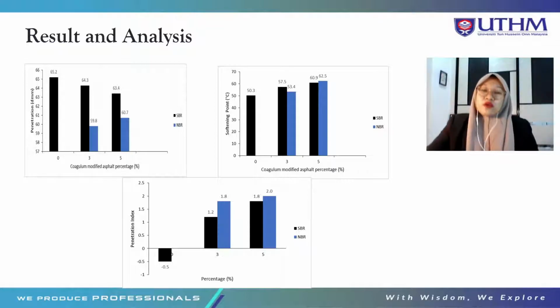The NBR coagulum modified asphalt binder shows a penetration value of 59.8 dmm with 3% NBR, while it is 60.7 dmm with 5% NBR added. The penetration value increased with increasing concentration of NBR. The second figure is the softening point result. The softening point will increase with the addition of SBR and NBR in asphalt binder.